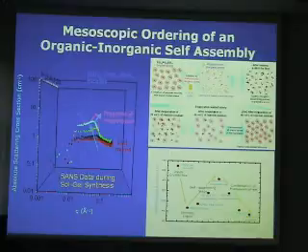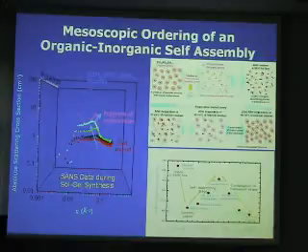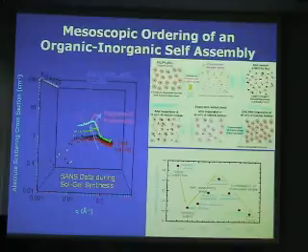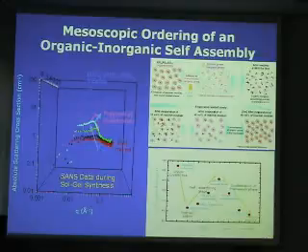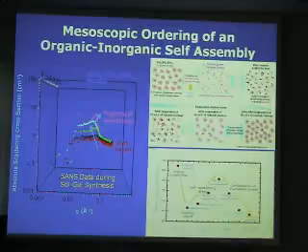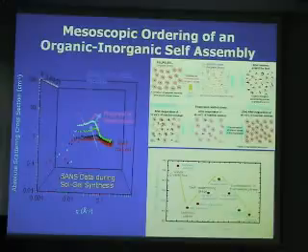But as you can see, the peak moving to the wide angle region is due to the polycondensation of the inorganic material, which decreases the intermicellar distance a little bit. Therefore, the peak goes to the wide angle region. The small shift to the small angle region during evaporation is due to the growing association of the organic and inorganic compounds during evaporation.